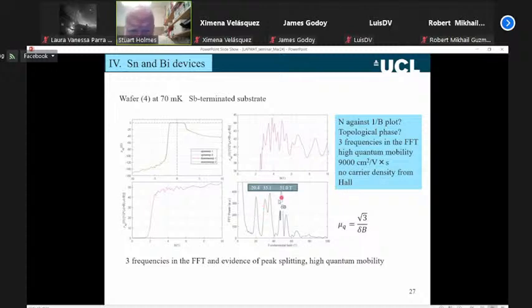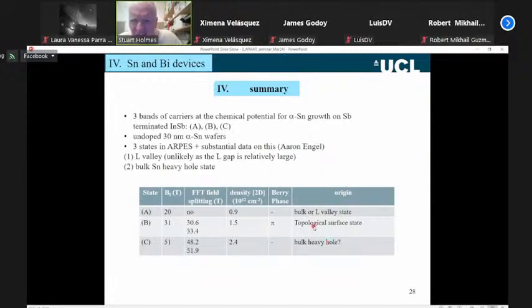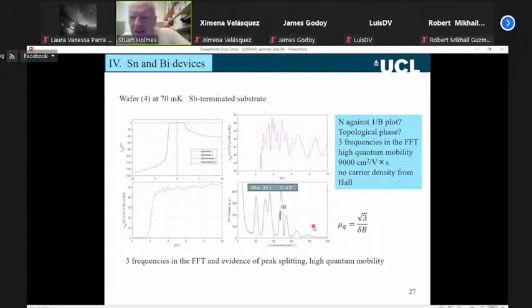If we Fourier transform this data, so that's the data on the bottom here. So this is Fourier transform power as a function of fundamental field. So we can see this split peak that we'd seen. We knew in the other device that this peak had a Berry phase, but we've now also got these extra features coming out in this particular wafer.